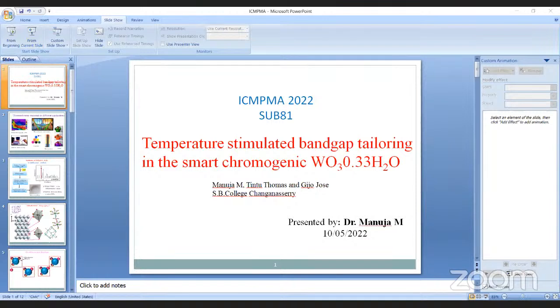The motivation behind this work is the different applications of thermochromic materials in different fields, such as smart windows, medical thermography, cosmetics, thermometers, etc. First of all, we prepared the sample via the hydrothermal technique from sodium tungstate precursors using a series of reaction steps, and the obtained sample is confirmed by X-ray diffraction. In the X-ray diffraction profile, you can see that the sample is phase pure and the orthorhombic phase is confirmed. The growth direction of the sample is along the C-axis, that is, along the 002 plane.